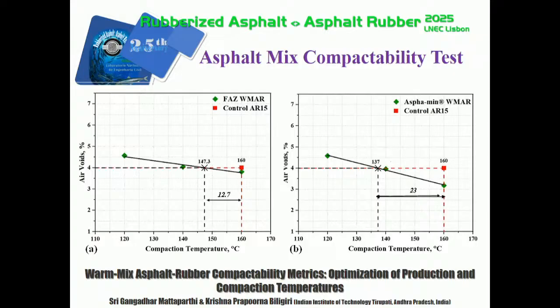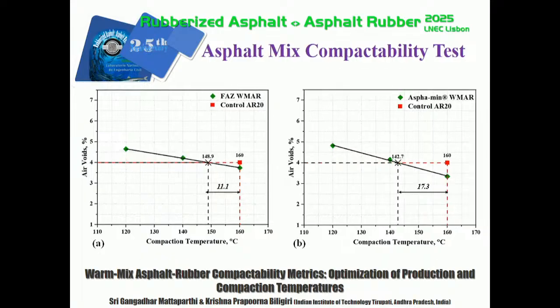Hence, the proposed method is reliable for knowing the metrics of warm mix asphalt rubber mixtures. Similarly, for AR20 binder, the fly ash zeolite gave about 11 degrees Celsius reduction, whereas the Aspha-min gave about 17 degrees reduction.